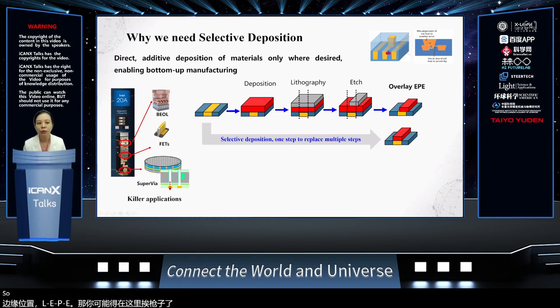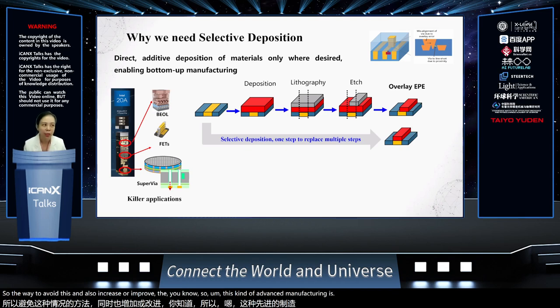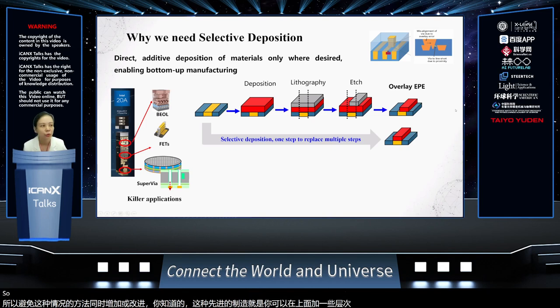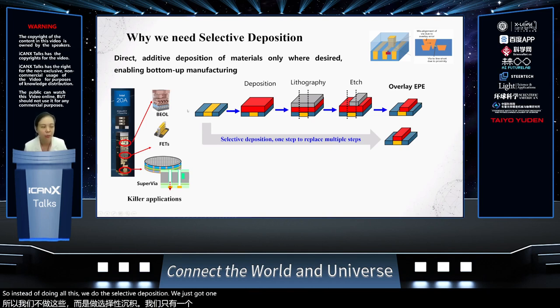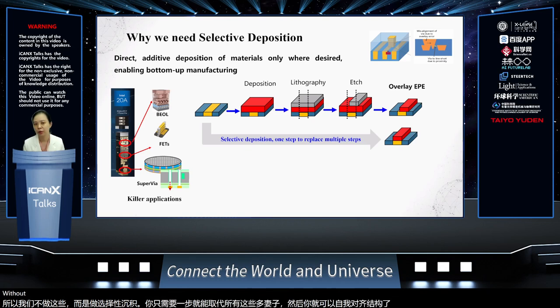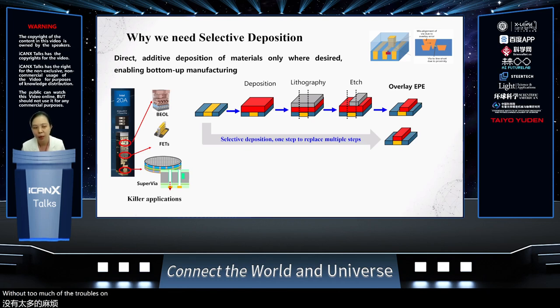So the way to avoid this and also improve the yield of this kind of advanced manufacturing is that you can add some layers on top of that. So instead of doing all this, we do the selective deposition. You just take one step to replace all these multiple ones, and then you get a self-aligned structure without too much trouble from edge placement errors.